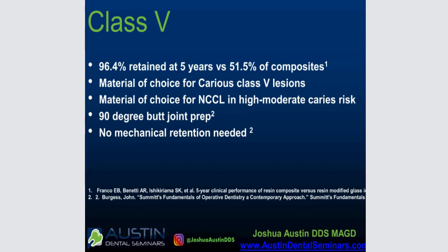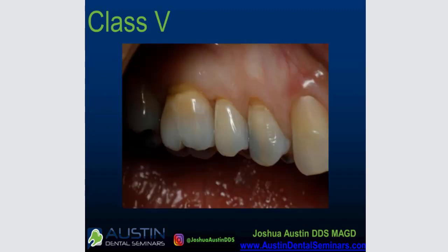The other issue is you don't really want to bevel the enamel, the occlusal part of your class 5, because that bevel on enamel is not really going to help you at all, because you're not getting enamel bonding with a GI or an RMGI. So just leave that at 90 degrees and roughen up that sclerotic dentin and proceed. And these work really well for those and hold up very well, even better than resin composite.